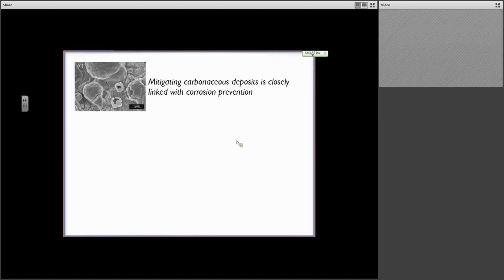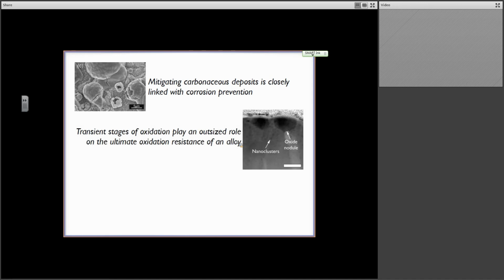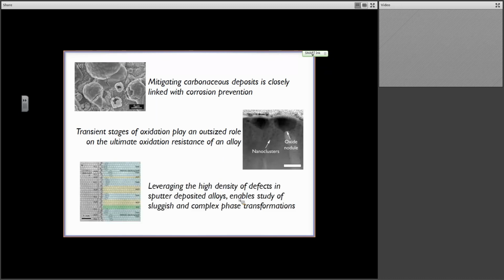Okay, so let's tie this all back together. We had three different segments of this particular talk. We started with a very applied and industrial space where we were looking at mitigating carbonaceous deposits on pipe steels by using a surface passivation to prevent the corrosion that is correlated with these carbonaceous deposits. We then spent a lot of time talking about how we actually form and control such an oxide on real materials by using these model thin film specimens. And so we could show that the transient stages of oxidation, if we can control those, we can control the ultimate oxidation resistance of an alloy without sacrificing the chemistry. And then finally, we had this little bit at the end where we talked about how these unique nanocrystalline structures might be useful for other things as well, including understanding sluggish or complex phase transformations that are also of interest to these sorts of extreme environments.